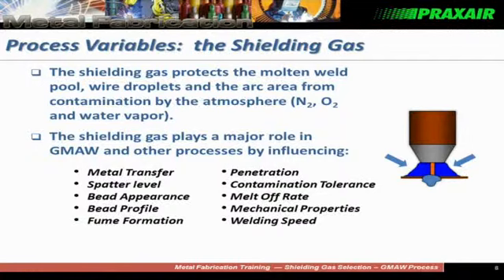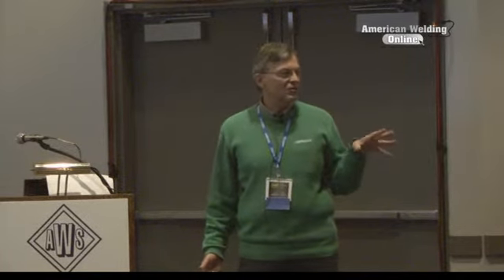So we're going to look at the shielding gas first. For those of you, many of you know if you've used a gas-shielded welding process, typically what is the shielding gas supposed to do? It's supposed to protect the molten material from being exposed to the atmosphere. But what I'll show you in a minute is that actually the shielding gas can control a whole host of variables: type of metal transfer you get, the amount of spatter that you might generate in the welding operation, all kinds of factors related to the appearance of the weld bead. So by matching the shielding gas selection with the consumable and the process, we can start to affect some of this optimization.